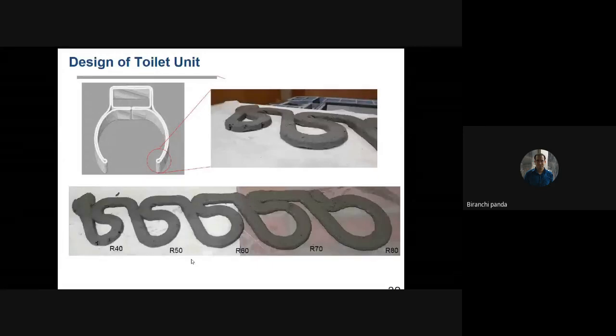So it means that here I am not talking about material, I am not talking about the process parameter. Rather, the design of the structure is very important and it can severely affect the property. As you can see, if we want to make a very small radius of curvature, you will have a tearing effect. But again, as I mentioned, this problem can be solved if you can optimize the process parameter or the material, because these three things are related: material, process parameter and structure.